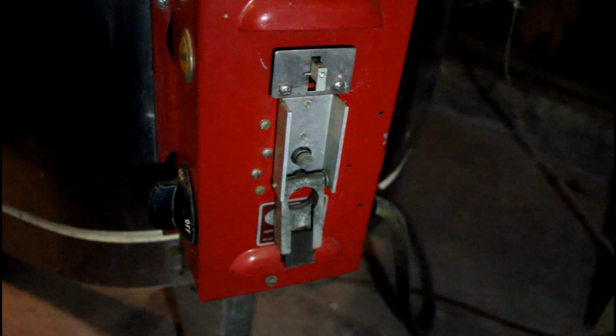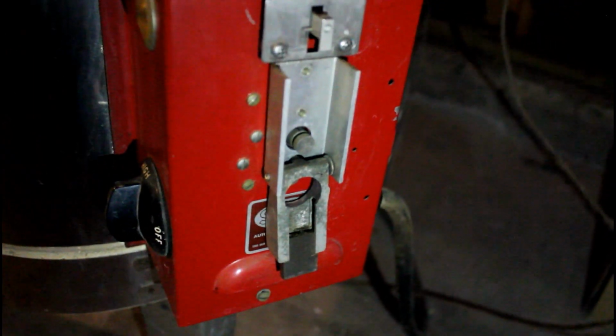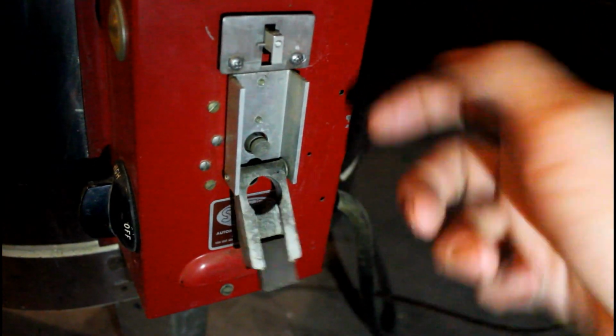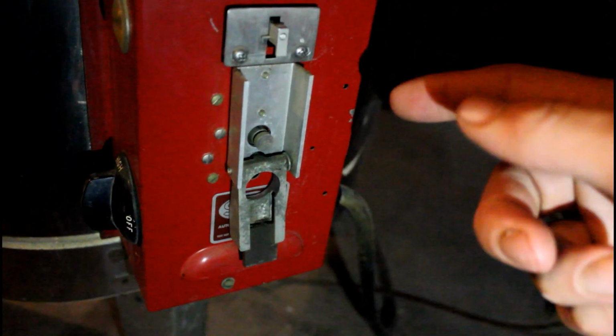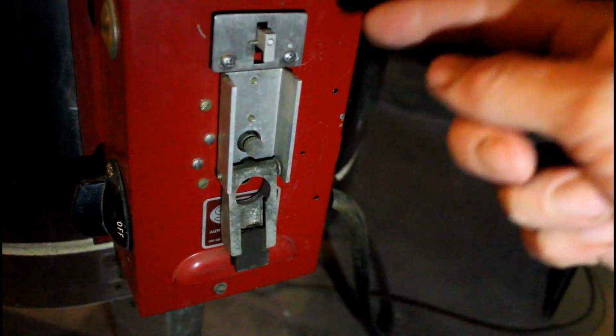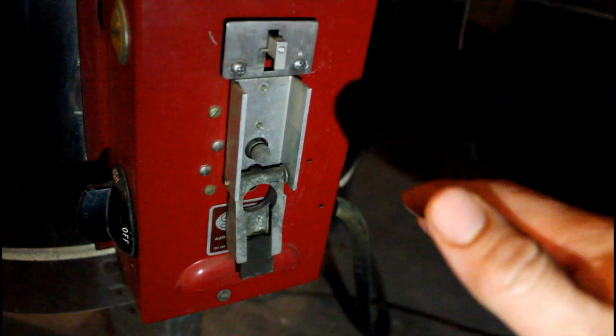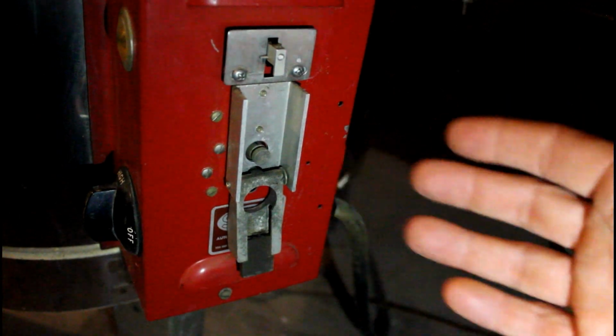All right guys, it's about 5 a.m. now, and you guys see this right here? This thing used to be like this, right? And now it's like this. That's because this thing tripped and the pyrometric bar and or cone on the inside melted, which is a very, very good sign. My bisque takes about 8 hours to operate, and the glaze takes much longer.